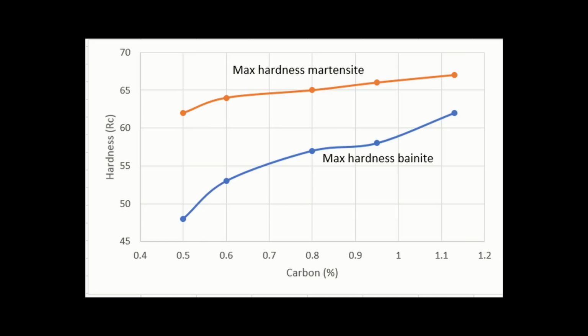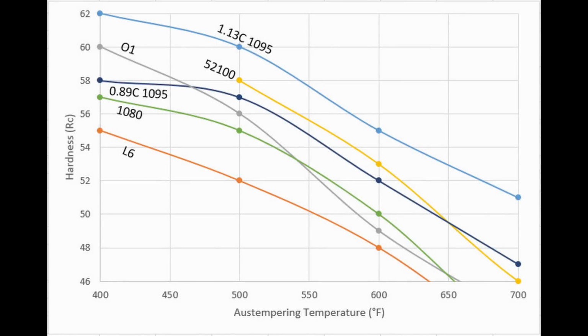With bainite, you have to have quite high carbon steel to be over 60 Rockwell, usually a 1% carbon steel. So while bainite can be tougher at equivalent hardness, bainite is usually not as hard as martensite. Now, what controls the hardness of the bainite is not just the carbon content, but also the temperature that you austemper at. So the temperature that we're quenching to and then holding.